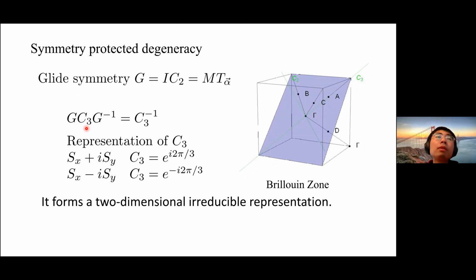Here, for our 2 bands in the system, they form the following representation of the 3-fold rotational symmetry, because the 2 sublattices both sit on the 6-fold axis. In particular, these 2 magnon bands carry different signatures of the C3 rotation. So you can see that if they belong to different symmetry representations of the C3 due to this glide symmetry, then this 2-fold representation should be protected by both the glide and C3 symmetry. This is why along the direction of gamma A you have a degeneracy of the 2 bands protected by these 2 symmetries.